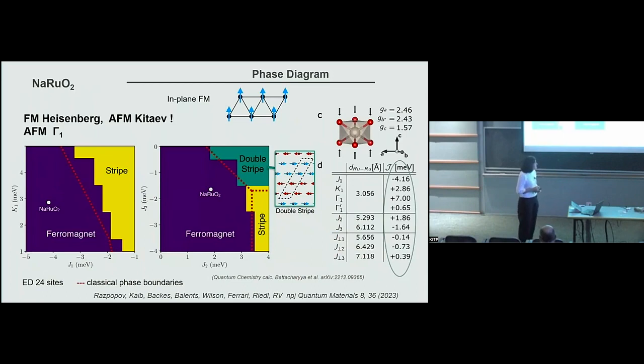Well, when you do these spin-orbit coupled systems, you cannot use the usual Curie-Weiss, because you have spin-orbit coupling, and therefore you have to use a temperature-dependent magnetic moment. So you have to do a different analysis than the usual one, and that's why I'm saying that we did this, and we find that we don't have enough data up to high temperatures.